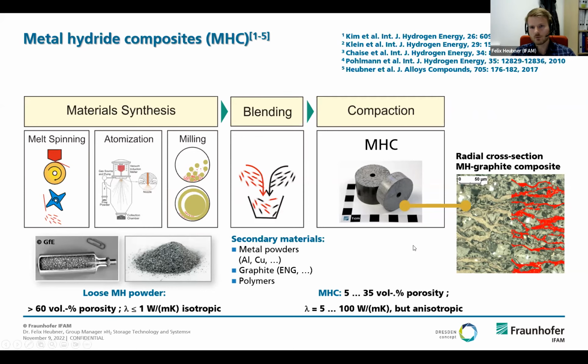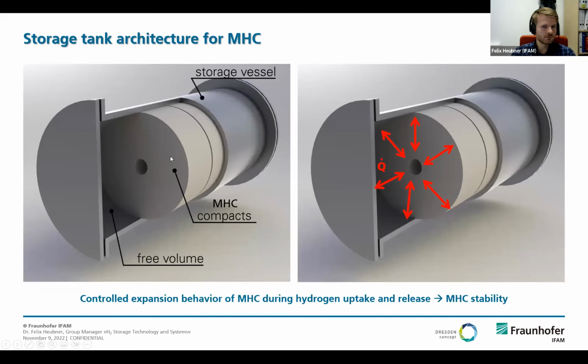When we look at the cross section of these materials, the tablets have an anisotropic thermal conductivity, because the materials inside sometimes align in radial direction. So that's nice for heat transport in radial direction to the outer wall of the pressure vessel. So how to integrate these materials? When we have tablets, we can think of some kind of cylindrical design of a storage vessel. It can be a tube bundle reactor as well, with easy scaling by parallelizing one pipe with following pipes. Inside this storage vessel, we have the compact materials, for example, these materials with higher thermal conductivity, and some free volume reserved for the volume expansion of the materials. So always taking into account heat management inside the material bed here on the right-hand side: transporting heat to the place of reaction and releasing heat when it is needed.